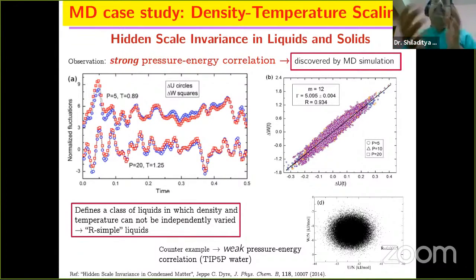So this discovery was done by MD simulation, and then people naturally tried to understand why. The first thing was that they tried to find whether there is any system where this is already known, and they found that yes, there is a system of special liquids called inverse power law models, or IPL liquids. In those liquids, the interaction potential goes as r to the power minus n. It's an isotropic potential, and one can show by calculating the partition function that you expect the correlation to be perfect. So the pressure and energy are not independent; they are proportional to each other. So you get a perfect correlation.